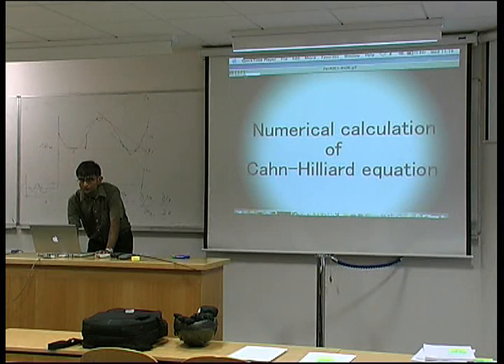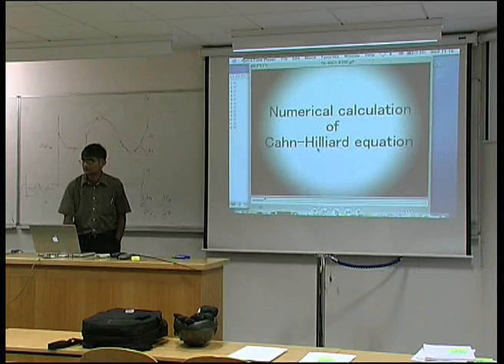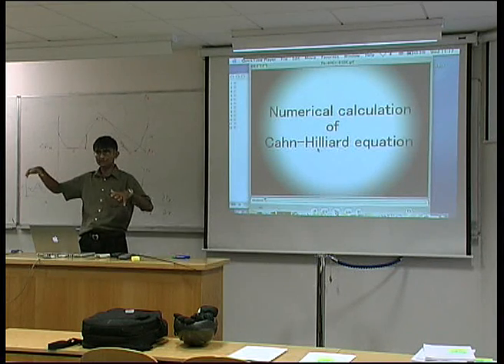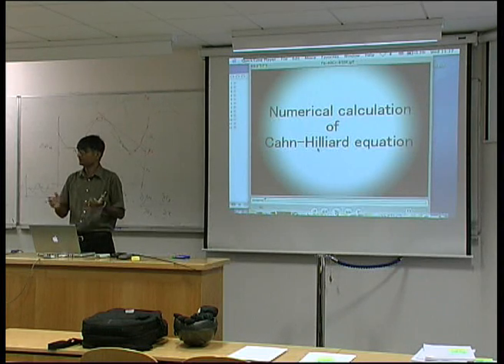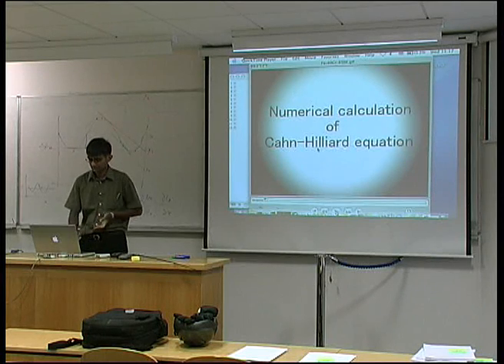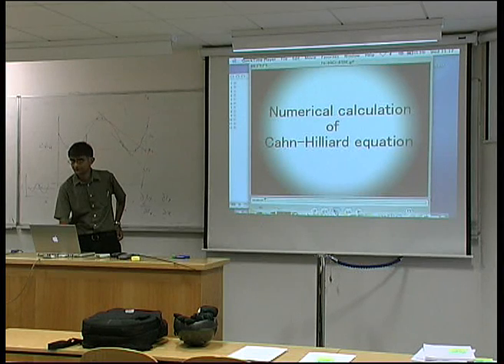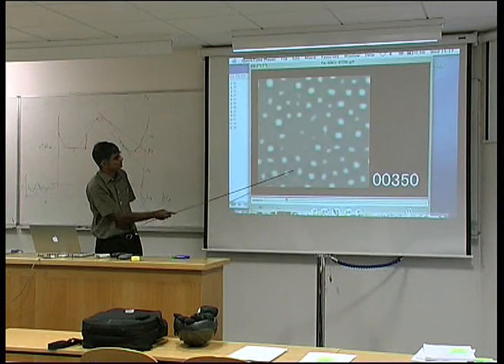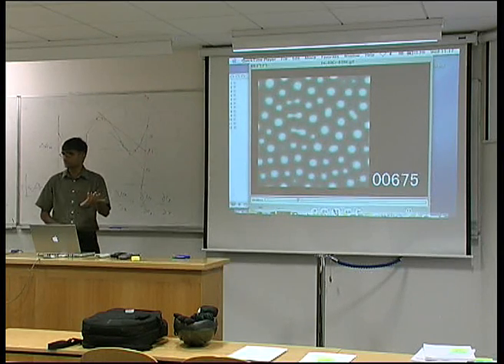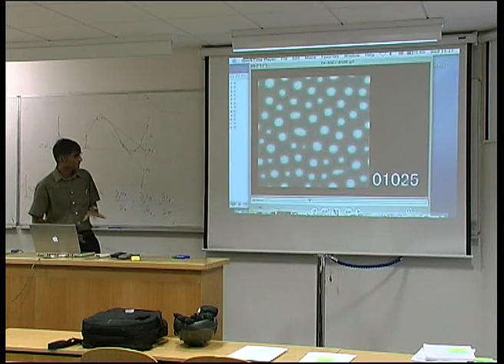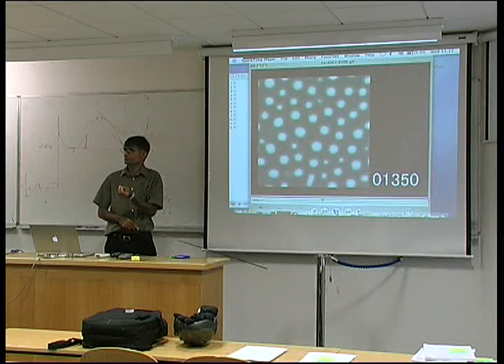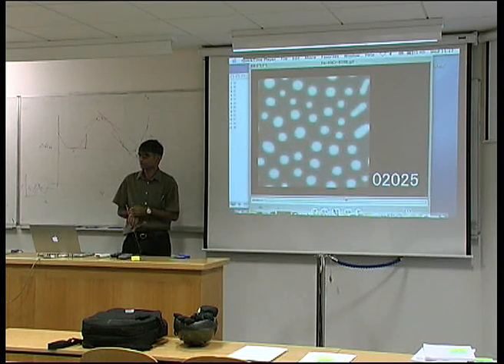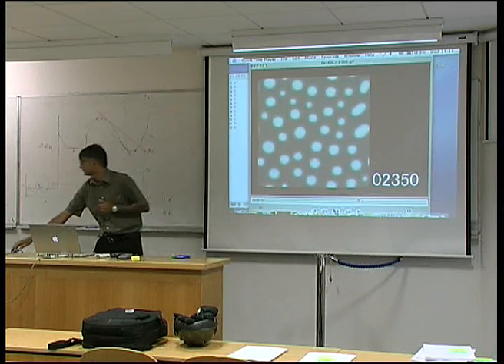Here's a movie that simulates decomposition in this region. Iron-chromium is a system in which the chromium atoms prefer to be next to chromium atoms and iron atoms prefer to be next to iron atoms - in other words, the enthalpy of mixing is positive. Starting with a completely homogeneous solution, we see chromium-rich and iron-rich regions developing spontaneously. It isn't that we are nucleating a phase, but it starts off with a small enrichment of chromium and that amplitude grows with time. We call this spinodal decomposition.